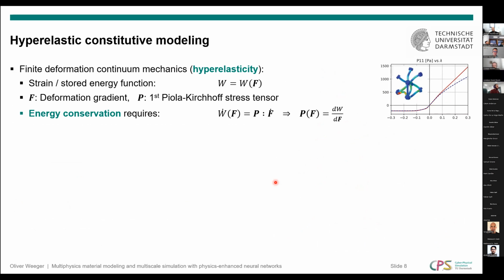So the next step, like I said, is to try to find a constitutive model, a material model that can represent this behavior. We focus on elastic behavior, which means that the deformation is recoverable, and we apply the concept of hyperelasticity, which is the default of modeling elastic material behavior in continuum mechanics. Hyperelasticity means that we assume that a so-called strain energy function or stored energy function W exists as a function of the deformation gradient. And when we take the derivative of this function with respect to the deformation gradient, we get the stress in terms of the first Piola-Kirchhoff stress tensor. And when we do that, we automatically ensure energy conservation, which would require that the rate of change of the strain energy is equal to the product of the stress and the rate of the deformation gradient.